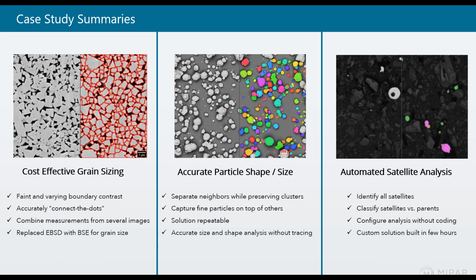And then in the last case, MIPAR, in under a working day, was able to provide this client with an automated solution, not just for finding particles, not just for separating the satellites, not just for classifying what's a satellite and what's a parent, but for providing a complete solution to take raw measurements and produce an automated metric of percent satellization that technically didn't exist inside of MIPAR until that very day. That solution was built from the ground up without coding for that particular customer.